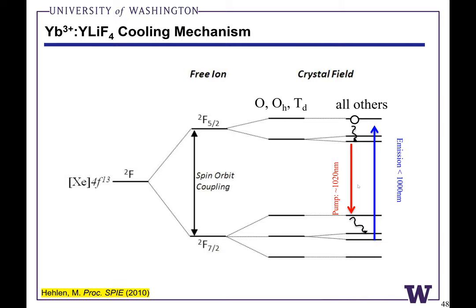You're effectively having the half-filled orbital, you can think of jumps from E5 to E4, and then more phonons can excite that configuration further, that you can imagine the half-filled orbital hopping to E3, to E2, and E1, and then spontaneous luminescence occurs. An electron will relax, any one of these three upper states can relax down to the half-filled state below and emit a photon that has more energy than what was absorbed. And that's really the core of this cooling engine, is sort of this phonon absorption and then spontaneous luminescence from the excited state.